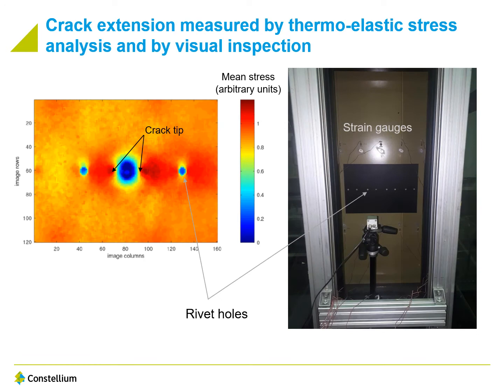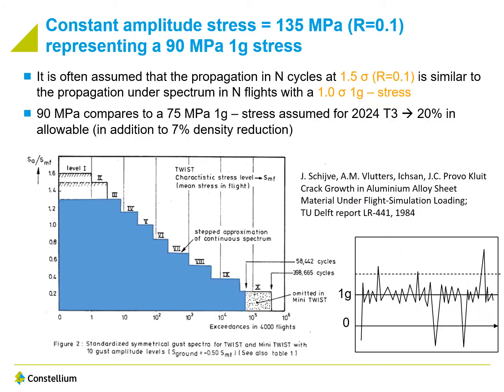For performing the test, we have used a thermo-elastic stress analysis in addition to visual inspection. This requires this black area where the thermal variations are monitored. You see the rivets, and you see as well the strain gauges that are used to be sure of the loads that we are applying. With a visual inspection periodically, we have monitored the crack growth in the panel. You see here the panel from the back, and the stringers are on the opposite side.